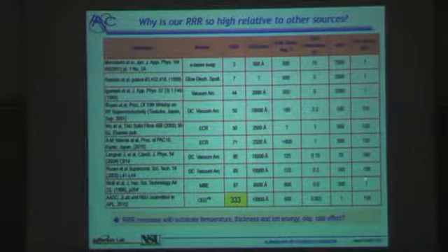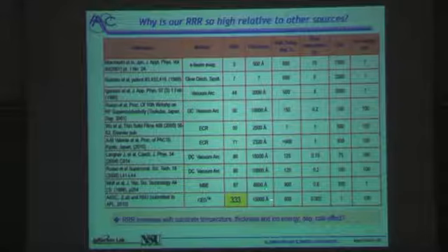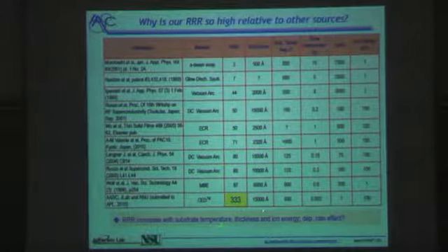It would have been a nice story if it weren't for this nasty exception here. This paper, where they used MBE, where obviously the energies are very low, they yet got a RRR of 87. But it may be because they heated the substrate to 900 Celsius. So you see this interesting combination of temperature, film thickness, ion energy. Might there also be a deposition rate effect?